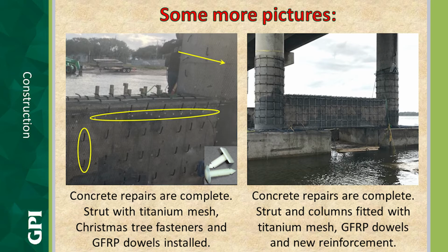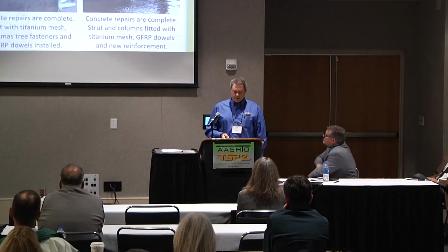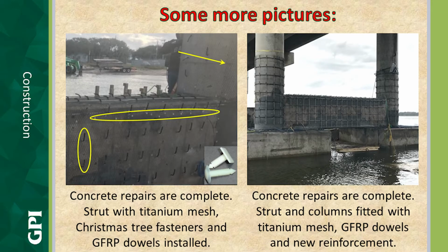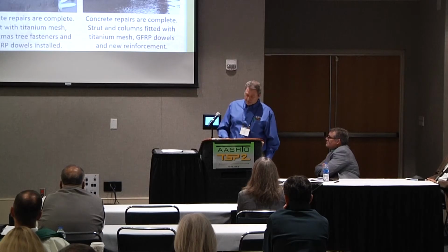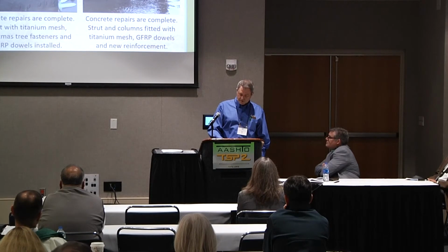On the left, the concrete repairs are complete, the titanium mesh anode's been installed, and it's being held in place with Christmas tree fasteners right here. You can see them in the picture. So they're holding the mesh tight to the concrete. The L-bars have been doweled into the existing concrete as well. On the right, the titanium mesh anode is in place. The GFRP L-bars are in place and tied to the newly placed reinforcement. Both of these are getting close to placement of new concrete.